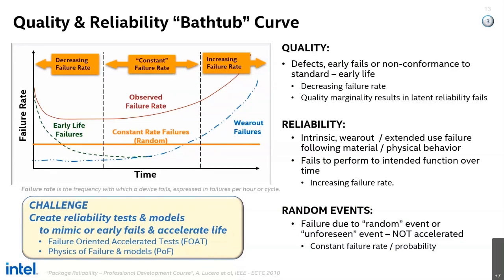In life or in use, you'll be seeing a constant failure rate. That means that there are random failures that occur. Neutron hits might be considered a constant failure. Neutrons are always impacting the environment here, or alpha particles getting cascaded. And then lastly, you have an increasing failure rate, which is related to wear out. And these tend to be intrinsic related failures. So our goal and our challenge is essentially in all these areas, in the early life, to accelerate the early failures and to accelerate the life failures. And we do this by the failure-oriented accelerated tests and through the physics of failure models.